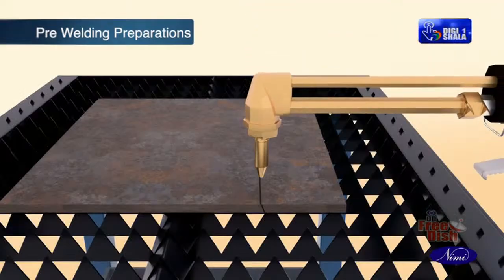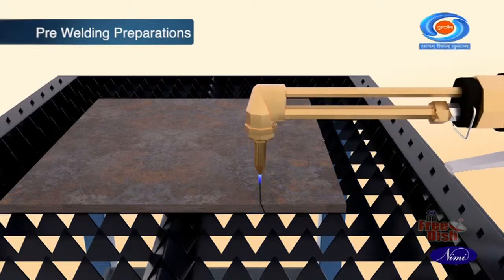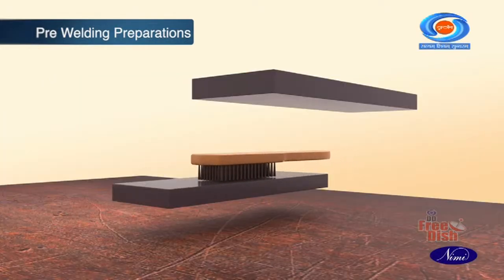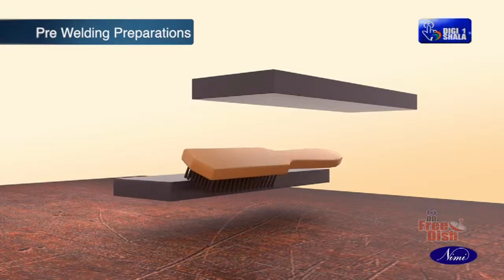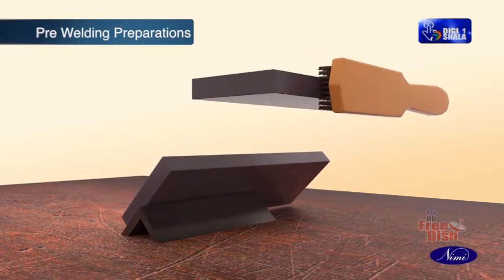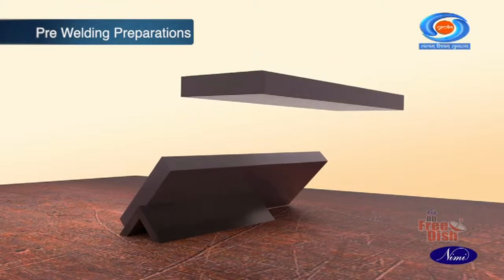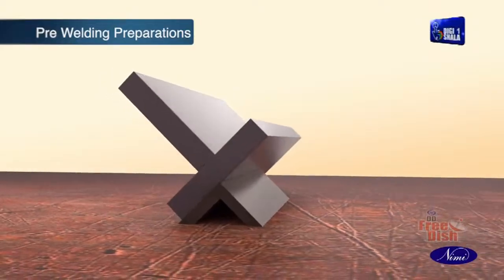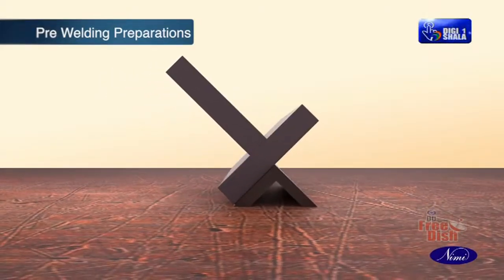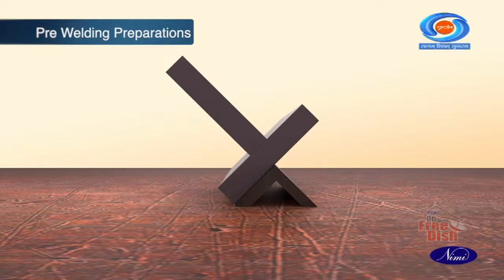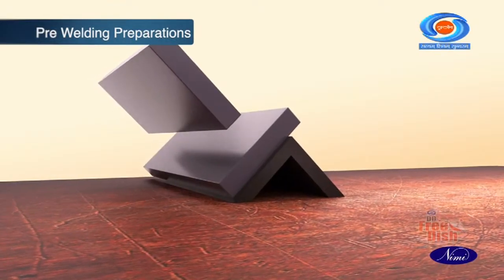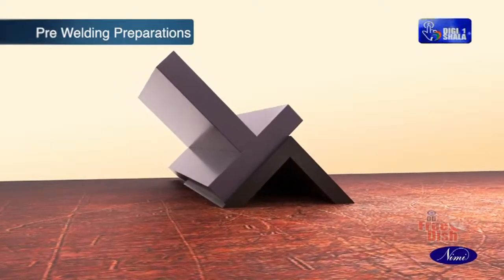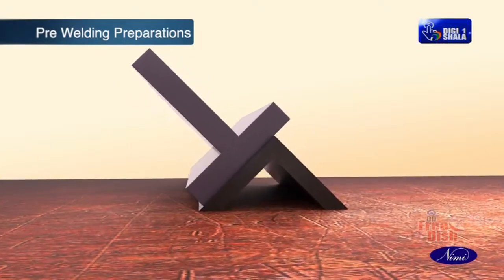Cut the plate by gas cutting. Clean the joining edges and surface of the plates and set the pieces in the form of T in alignment forming 90 degree between the plates. This presetting to 90 degree is done to compensate the effect of shrinkage forces when weld deposit cools down. Preset the pieces to have 90 degree angle between the plate surfaces and give a distortion allowance of 3 degrees.